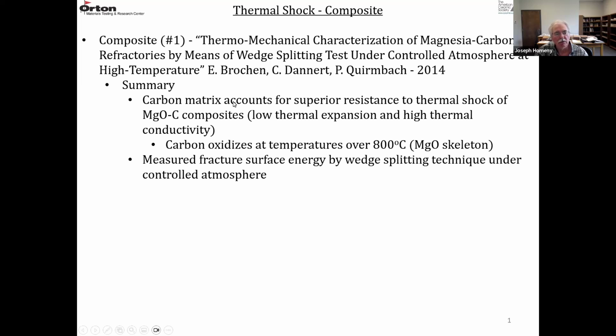Basically, these carbon matrix composites have superior resistance to thermal shock. The one I'm looking at today is an MgO carbon composite. That's the primary lining for a lot of steel vessels, especially the basic oxygen furnaces. These materials have low thermal expansion and high thermal conductivity. Both of these characteristics give good thermal shock resistance.